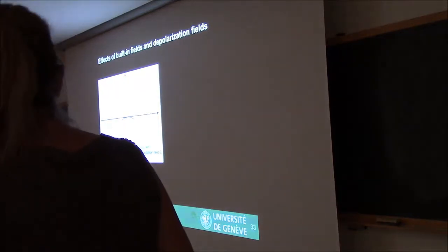But in materials, I've been talking a lot about the depolarization field. What you also have to keep in mind is that it's not always symmetric. You might have a field that is due to the interfaces, due to the fact that you have different interfaces and so on. And so you can also have a fixed field that is independent of the polarization. This fixed field, we call it the built-in field. It will favor one polarization over the other, and so it will make this energy double well asymmetric.